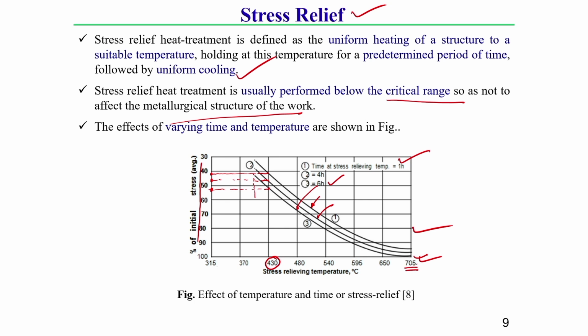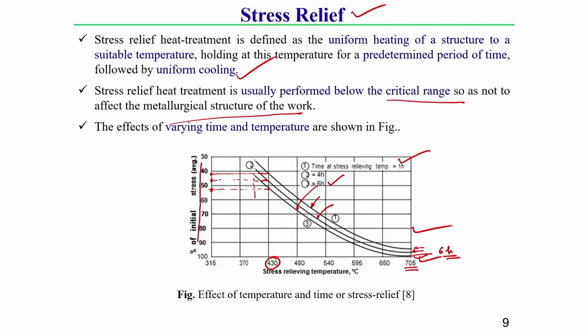Further, for a particular holding time or soaking time, if we increase the temperature, like let us say 705 degree centigrade, what you can observe, for 6 hour soaking time you can get around 100% residual stress relief, whereas for 705 degree centigrade for 4 hour soaking time you will get a percentage of relief of residual stress around 98%. If we further reduce the time, then the residual stress reduction also decreases. So, what we can observe from this curve, by increasing the post heating temperature and holding time, we can relieve the residual stress from the weld specimen drastically, understand.